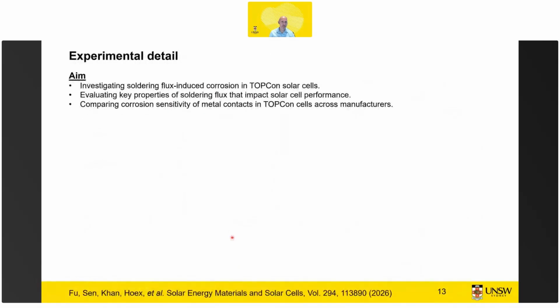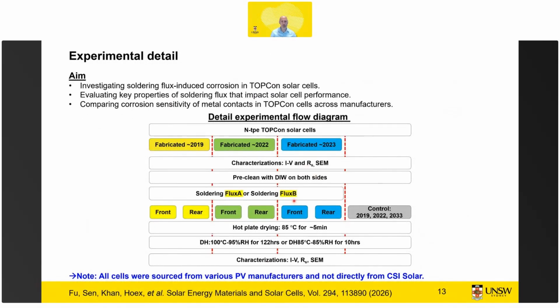And if we then look at particularly flux, we tested TOPCon solar cells in this case. So this work was just published earlier this year. And we took TOPCon solar cells vintage 2019. So that's when TOPCon just started to be entering high volume manufacturing. 2022, when the pace was really picking up. And 2023, just before the introduction of laser-assisted firing, mostly referred to as LECO. And we exposed the cells to two types of soldering flux, so flux A and flux B. These were fluxes that were used widely in the industry.